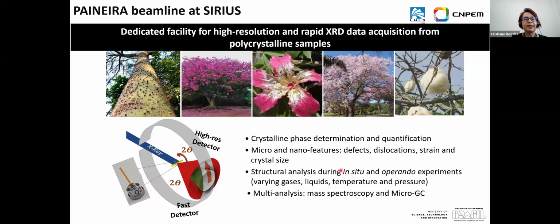You can study the sample under in situ or operando experiments. This encompasses the kinetic experiments that I mentioned in the slide before, and it's when you use the sample environment that was shown in the first lecture today. And we also offer gas analysis for your sample. So you can connect a mass spectrometer or a micro GC to determine how this gas fluid has changed after going through your sample.